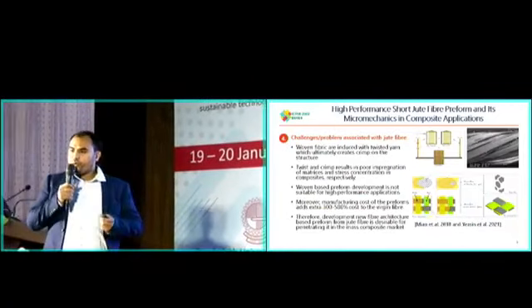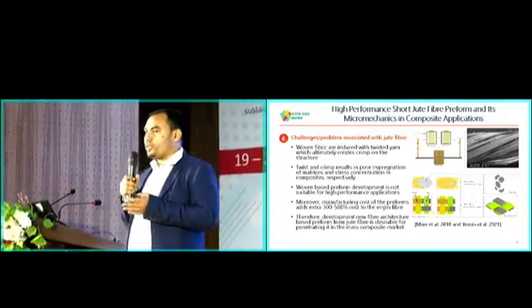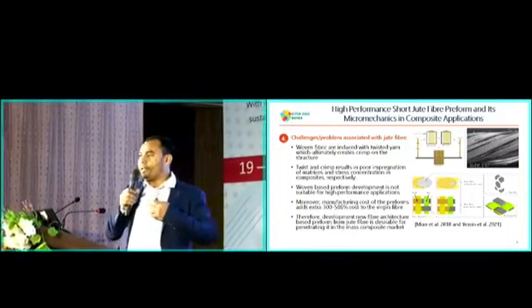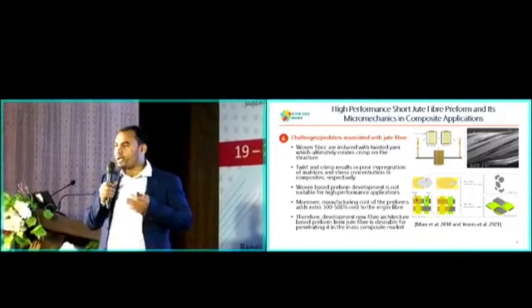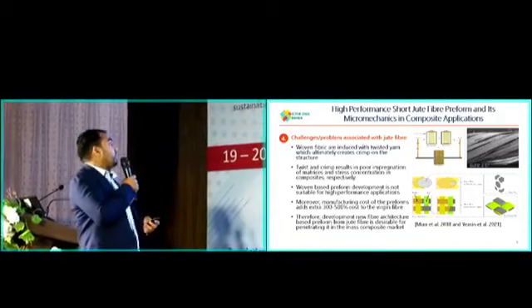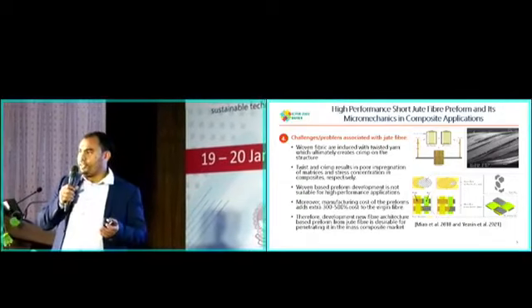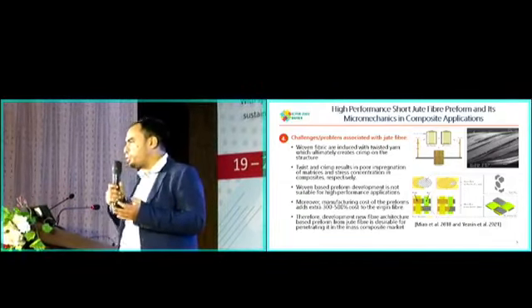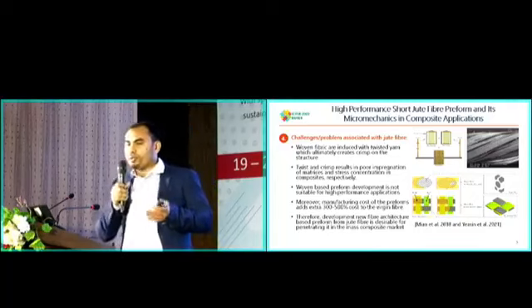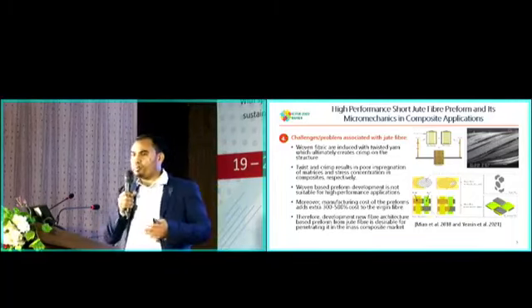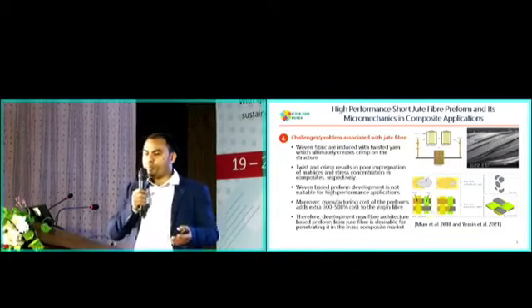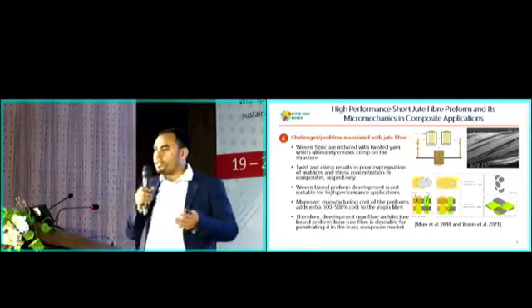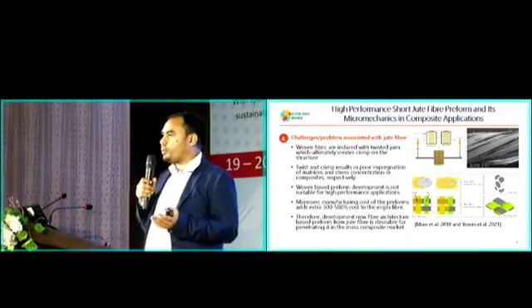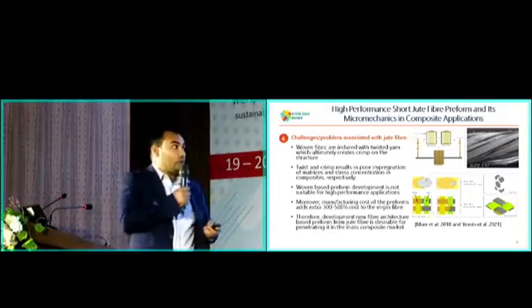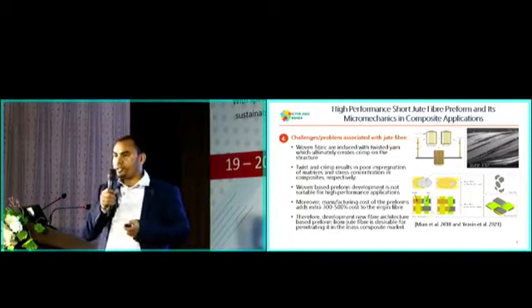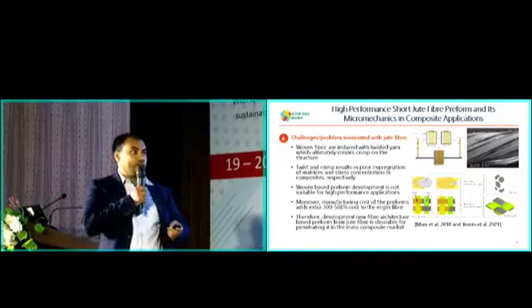Before starting this project work, we also thought about the challenges and problems that we may face in developing a novel kind of architecture for this project. We found that the traditional materials received from the industry come with twist and crimp. As you know, the twist present in the fiber doesn't allow proper impregnation during the infusion process. Also, the crimp present in the fabric produces stress concentration, which prevents reaching the maximum mechanical properties. So we avoid using the virgin materials, and also the textile structures existing in different industries.